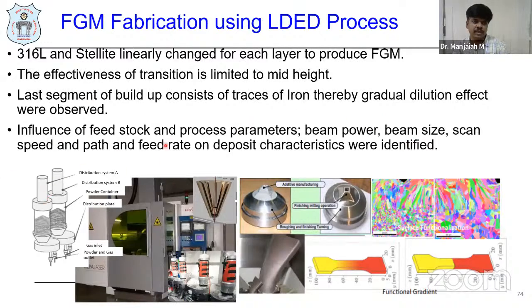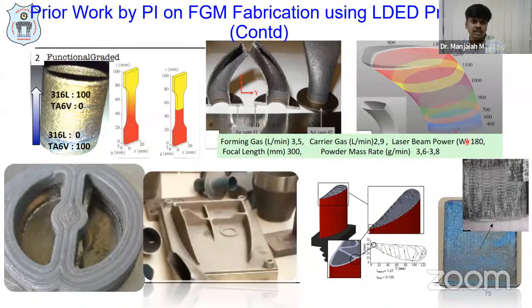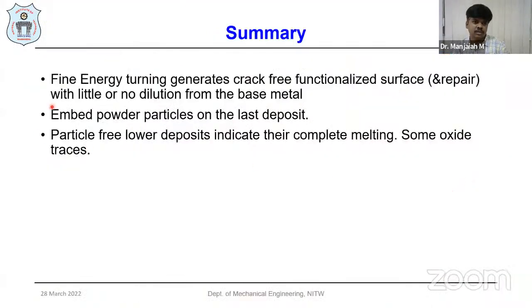And some functional graded materials we have fabricated for the oil and gas industry. These are all functional graded parts which are fabricated. With respect to the final view or conclusion, fine tuning of energy for generating crack-free functional surfaces with little or no dilution from the base metal is required. Even some of the embedded powder particles on the last deposited layers can be minimized by controlling the process window, and particle-free lower deposits indicate complete melting, and some oxide traces will be there.